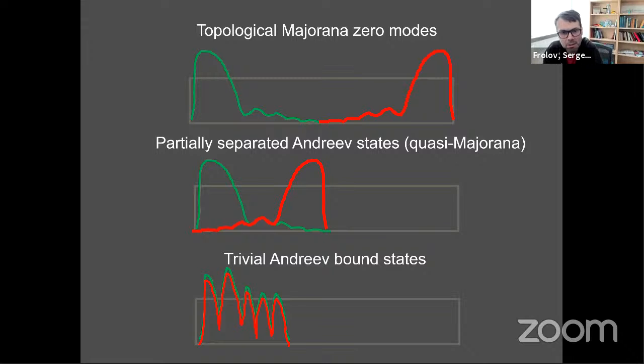There are also several different gaps that I'm used to, but I did a poor job introducing. But basically, it's a metal semiconductor interface. The metal only goes superconducting at the lowest temperature, like 1 Kelvin or 5 Kelvin, something like this. And the semiconductor is doped typically into the conduction band. So you just sit above the gap by a few tens of millivolt, or just a few millivolt in the best case, above the semiconductor gap. And then you open a much smaller gap. So the semiconductor gap would be, in this case, 200 millielectron volts, 0.2 volt. And then you open a 200 micro electron volt gap, which is 1,000 times smaller, around the Fermi energy that sits in the conduction band.